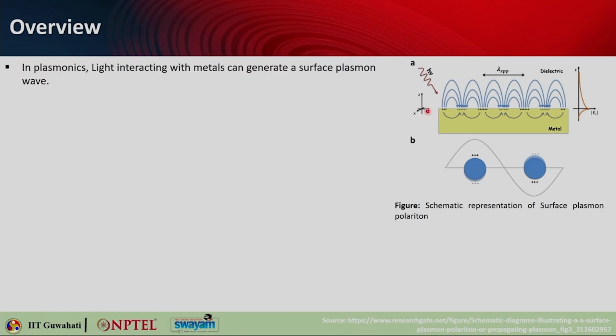This is an example of how you can excite surface plasmon polariton propagating along a metal dielectric interface when some light is falling. But the one thing not shown here is that it cannot be directly excited by simply shining light on the interface. You have to have an arrangement of phase matching, either using a prism or a grating.